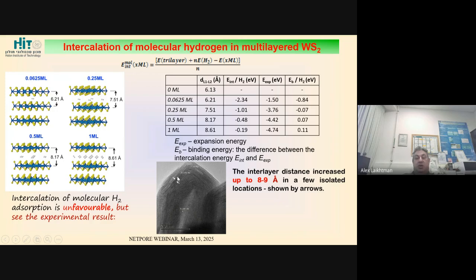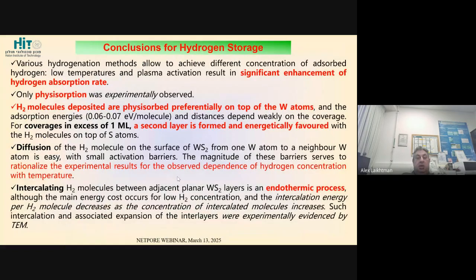I'm not showing you here the calculations for atomic hydrogen, because for atomic hydrogen you have to somehow dissociate hydrogen. There is some plasma dissociation, but the percentage of atomic hydrogen dissociated by RF plasma is very, very low. Otherwise, you would have the bottle of atomic hydrogen, the process will be very, very favorable, and probably we could have a lot of hydrogen, but I don't have such a bottle. We should have a kind of atomizer to bring the hydrogen to dissociation, which consumes a lot of energy. So from various hydrogenation methods, we proved that the plasma activation is essential. So we continued with RF plasma.